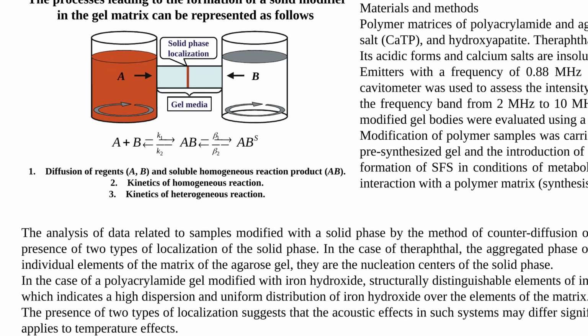Ultrasonic irradiation was performed at frequencies of 0.88 MHz and 2.64 MHz, with intensities of up to 3 watts per square centimetre. Cavitation intensity was evaluated using a cavitometer. The device records broadband acoustic noise in the frequency range from 2 to 10 MHz, using a broadband hydrophone. Temperature effects in the modified gel bodies were evaluated using a pyrometer.